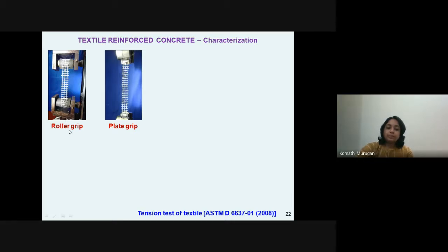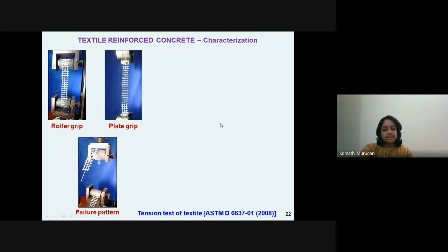So if we want to test the flexible textiles, what we use is a roller grip at the ends. In order to hold the textiles, we roll the textiles at the ends, we grip it, and that is the roller grip system. The flexible textiles can be rolled because they can be bent. But if we want to test the stiff textiles, which are, for instance, the ones coated with epoxy, what we do is we clamp aluminum plates or cardboards at the edges of these textiles, and we clamp them together in the grip systems of our electromechanical test device. The tests are conducted as per the ASTM D6637 standards.